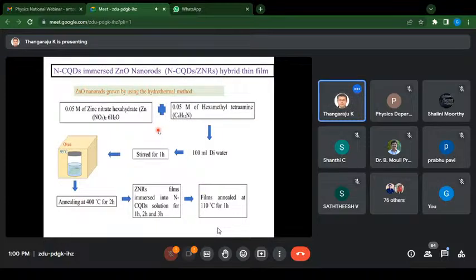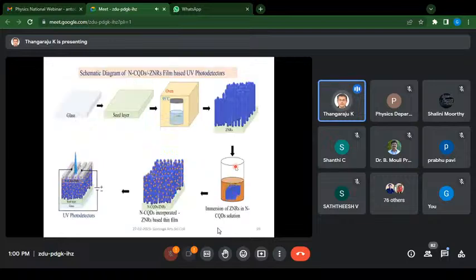So this is the process by which we made the zinc oxide nanorods and immersed them into the carbon quantum dots. It means we made the carbon quantum dots adsorbed onto the prepared zinc oxide nanorods, and this nanorod carbon quantum dots based hybrid thin film is used in the photo detectors. So you can see that the nanorods are grown onto the zinc oxide seed layer, and the grown nanorods are immersed in the carbon quantum dot solution, and we observed that the immersed zinc oxide nanorods give better performance in the UV photo detectors.